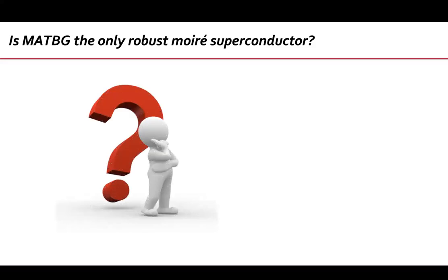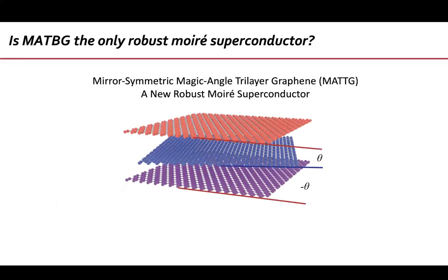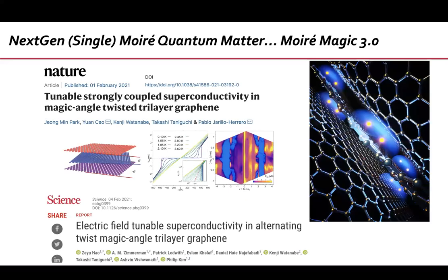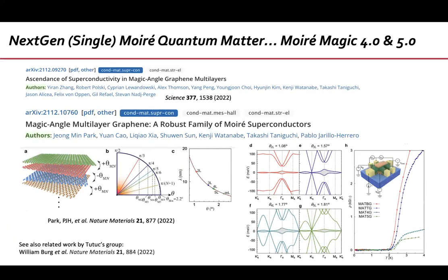So the question for a while was, maybe magic angle twisted bilayer graphene is a special case, due to the special topology or especially flat bands or who knows what, and it's the only robust Moiré superconductor. Now we know that the answer to the question is no. At least there is one more system, mirror symmetric magic angle twisted trilayer graphene, which is a new robust Moiré superconductor. I showed this yesterday: both the group of Philip Kim and myself showed, a couple of years ago, that twisted trilayer graphene at the magic angle is a very robust superconductor. And last year, we also showed that four layers and five layers at the magic angle are also robust Moiré superconductors, with all the things that you want to check, and this has been reproduced by many groups.